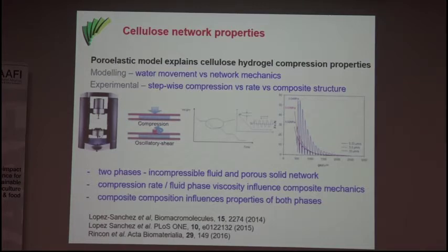So that's slow versus fast. So this is an important concept, we think, here. And what can affect that is not just the strength of the polymer network, but the viscosity of the liquid phase. So if you've got a viscous phase, that's not going to move out of the way so quickly either. So a viscous solution phase or a strong solid phase, the interactions between those really determine this poroelastic response.